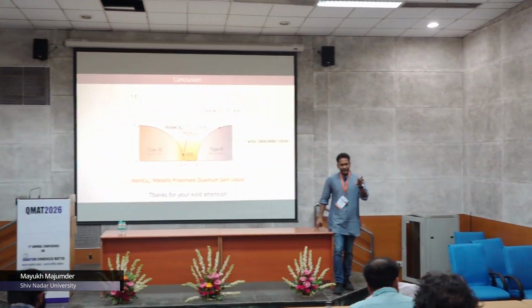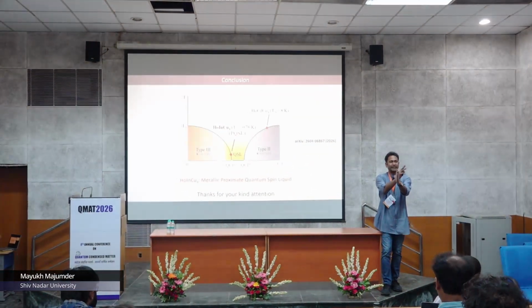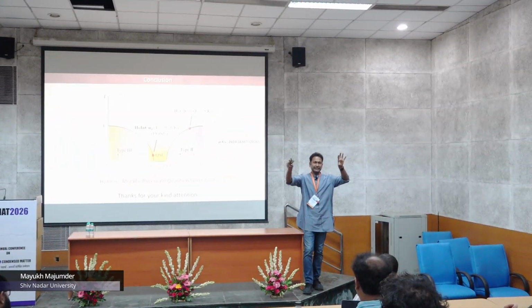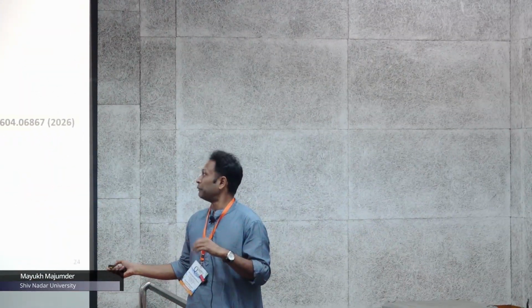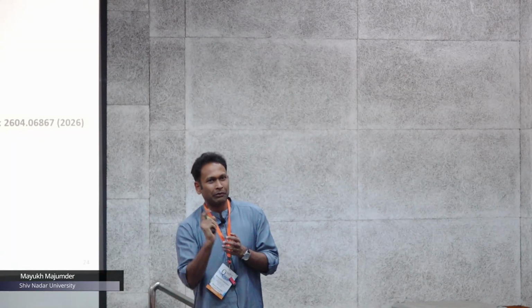So, in the case of the FCC lattice, maybe the theoreticians may give you more information about it. Whatever I have seen, the theoretical results that I have shown are only on insulating systems. They didn't consider the quantum lattice model or other models related to metals. But in this particular case, what I can say is that for the FCC lattice, the regime where there is a phase boundary between two different states is very tricky to deal with, because there are multiple degenerate states around. We are definitely expecting it, but there are only two papers that hint there might be a spin liquid, and no detailed study to the best of my knowledge.